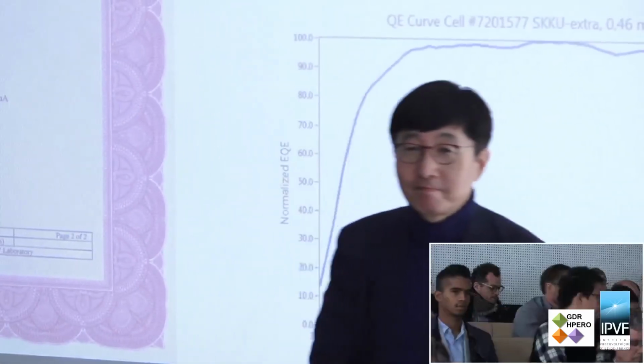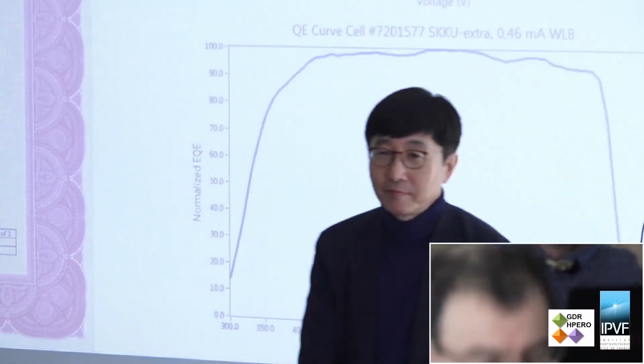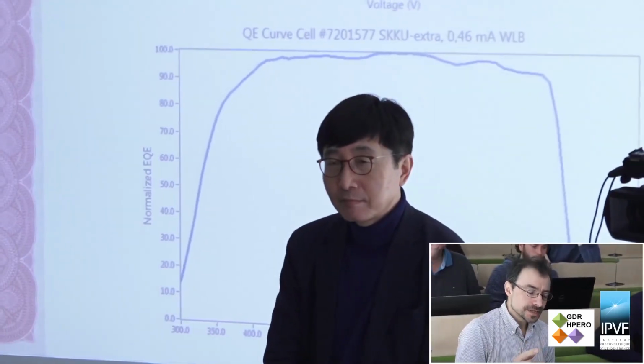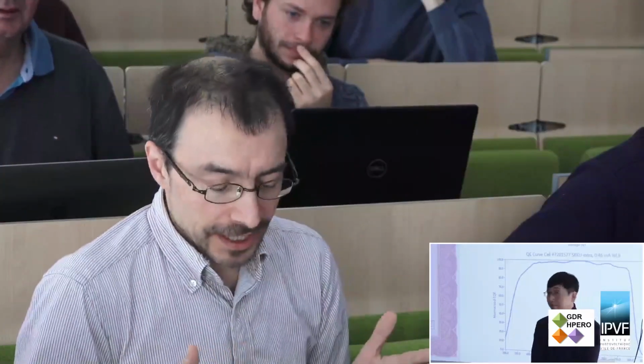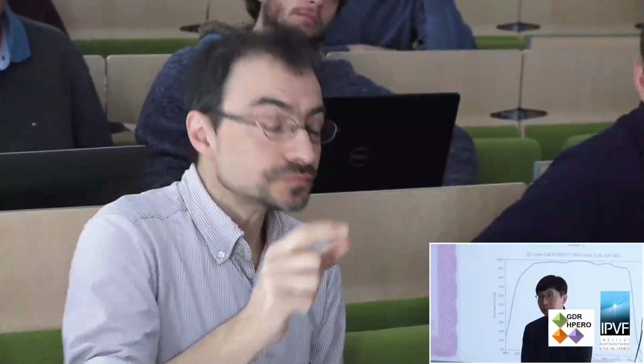Thank you very much. A very nice presentation. It was a wealth of results and very impressive. I'd like also to come back to one experiment, where you show that the PL decay or the PL intensity changed when you apply a small voltage across a channel of perovskite, similar to my colleague. I could infer from your slides that such a small voltage as 0.5 volts dropped across a huge layer would still result in a considerable drop in PL intensity. So even for the potassium iodide, isn't that bad news also for the stability? And I don't know how to relate that to the efficiency, where you show that it's stable, and you have a much higher voltage bias across the cell, in your IV curve. So how could you, yes?